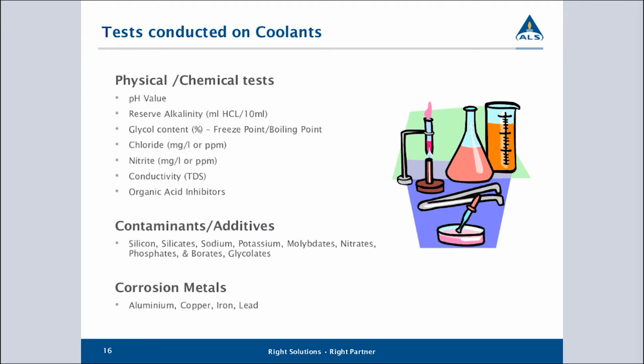We can measure things called reserve alkalinity. We can measure the glycol content, chloride content, nitrite content, conductivity, and quantify the organic acids that are present in the coolant. We can also look for contaminants in the cooling system to see anything that might be getting in there that shouldn't be in there. And then importantly is to monitor corrosion. If we can monitor the metals that are present in the system, if we see those metals starting to be dissolved into the coolant, that is a strong indicator that corrosion is occurring within the system.